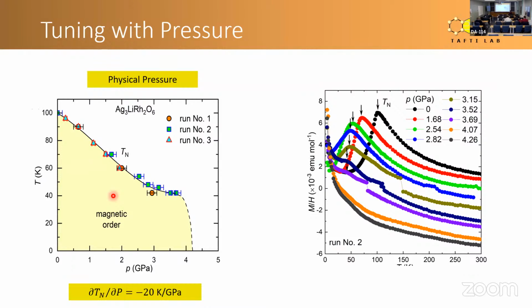When we do these experiments, the susceptibility data has the susceptibility from the sample as well as the susceptibility from the pressure cell itself, which is paramagnetic. We need to subtract the pressure cell susceptibility. It's a paramagnetic susceptibility, it's boring, but you have to subtract it anyway. And it is that subtraction, near zero, that often gives you a jump in the data. It's just due to the fact that we're subtracting the pressure cell.